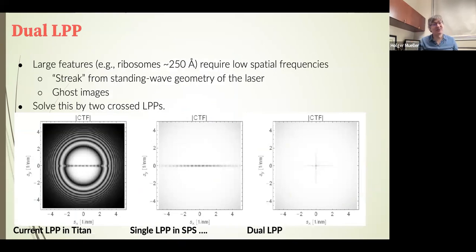All right. The CZI microscope will also feature a dual laser phase plate that will, and here you see the simulated contrast transfer function of our Titan. So bright is better, dark means no contrast. And you can see that the contrast drops rather quickly at high spatial frequency from aberrations. These will be gained with monochromation and aberration corrections. The rings in the spatial contrast transfer function will also be gained. And finally, you see the streak here. This streak is the consequence of the linear geometry of the laser beam. Using dual laser phase plates replaces the one streak by two streaks. You would think that is worse, but these two streaks are much, much less pronounced. So that addresses this issue.